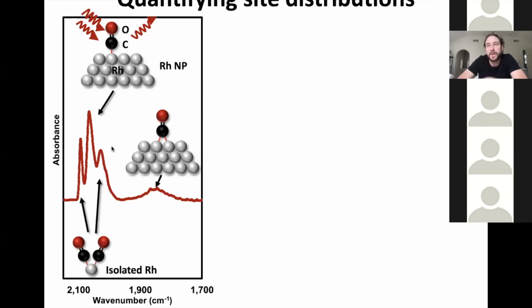I oxidize the catalyst to remove ligands remaining from depositing my salt. I mildly reduce it in hydrogen at, say, 250 C, so that I take any oxidized rhodium clusters and convert them to metallic rhodium clusters. And then I adsorb CO at saturation coverage at ambient temperature, or even below ambient temperature. Then I take an infrared spectrum of this system, and I get all these different beautiful bands.